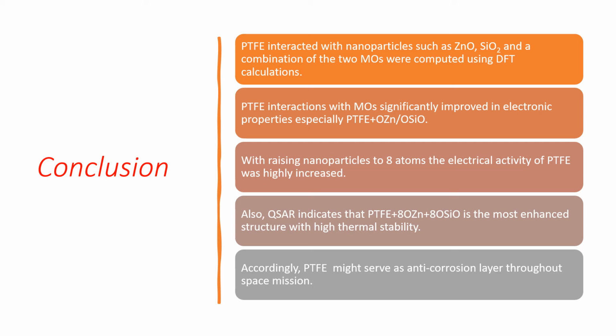With rising nanoparticles to 8 atoms, the electrical activity of polytetrafluoroethylene was highly increased. Also, quantitative structure activity relationship indicated that the structure of polytetrafluoroethylene with 8 atoms of zinc oxide and 8 atoms of silicon dioxide is the most enhanced structure with high thermal stability. Accordingly, polytetrafluoroethylene might serve as an anti-corrosion layer throughout space missions.